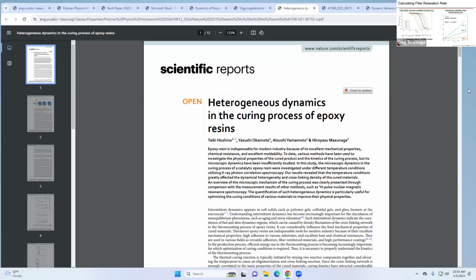Gamma is a stretching or compression exponent. So simple exponentials always decay down at a certain rate, but sometimes there's other dynamic timescales that define that process. So you may have to stretch or compress the exponential, and we can do that by that power factor right there, right? And we found that that mattered, right? These are not simple exponential decay functions. They're actually kind of more rich in their physics, so we had to apply that function.